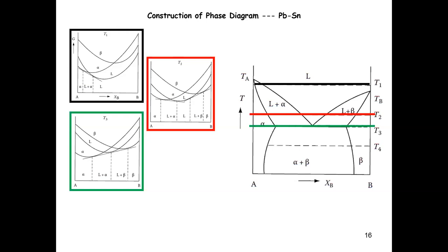So at this very unique temperature, how many phases can coexist in this scenario? Three, right? Because the atoms in all three phases share exactly the same chemical potential. So here you have three phases that are in thermal equilibrium, so they coexist. Does this make sense, everyone?